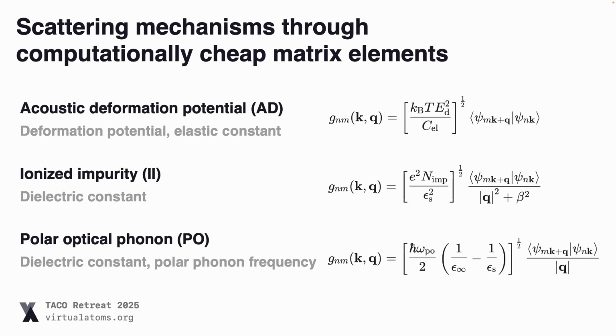And then what we do is that we use scattering matrix elements which are based on easy to obtain materials parameters. So in AMSET we have support for at least three different types of scattering mechanisms: acoustic deformation potential, scattering from ionized impurities, and scattering from polar optical phonons. We also have piezoelectric and some others as well. But to calculate each of these scattering rates, all you need is the deformation potential, which is relatively straightforward to obtain from a series of strained calculations, the elastic constant, which is again easy to obtain. And in fact, I showed before that we have calculated thousands of them for the Materials Project. The dielectric constant, which is very quick, and also the polar phonon frequency, which again we can get from a dielectric constant calculation essentially.